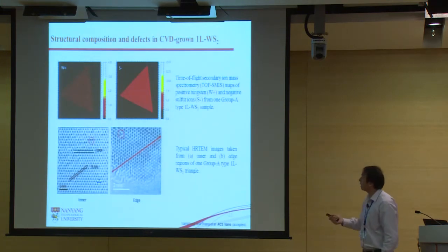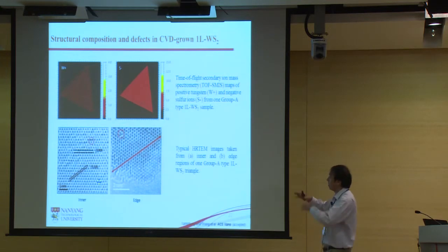Okay, we try to understand why, again, the non-uniform sample has such a variance of light emission, and we think there's some sulfur vacancy along those dark areas, for example, the three backbones there, and we try to find some evidence, and here it seems we have some evidence.